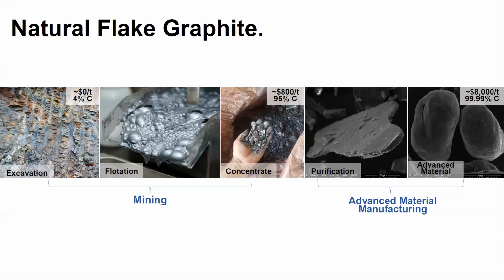So as we look at this process, which I've got laid out in the slide, going from left to right, the process would typically start by mining the rock, in this case, a graphitic schist containing approximately 4% graphite or carbon. So the rock is excavated, it's crushed, and then the graphite is separated through a series of flotation and polishing and grinding stages, which results in producing a graphite concentrate that is now approximately 95% carbon. At this stage, the material could be sold into the traditional industrial markets after the flakes are sorted by size.